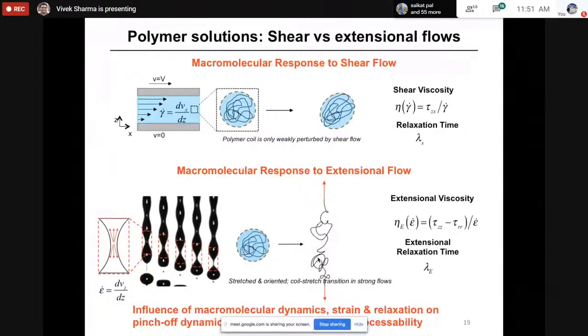However, when you try to stretch the liquid bridge, or if you try to pump it through porous media, because of high extensional viscosity, the same fluid in extension starts to behave like honey. If you try to do dripping, it will have a very delayed pinch-off. And this is something that really needs to be emphasized again. Polymer solutions can behave like honey in extension, even if they behave like water in shear. The hydrodynamically extended object, the stretched chains, if you stop the flow, again try to get to the unperturbed coil state, but it takes much longer time, especially in dilute solution, to get to this preferred state. And the time scale now is called extensional relaxation time.